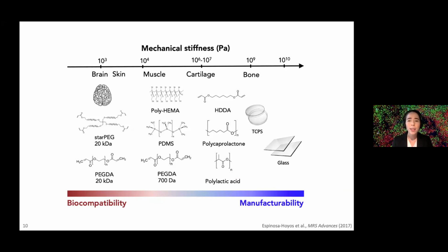So what I did was develop hybrid hydrogels formulated with hydrophilic and high molecular weight polyethylene glycol precursors commonly used in biological applications, and hydrophobic and short acrylates commonly used in microfabrication for their efficient polymerization kinetics.